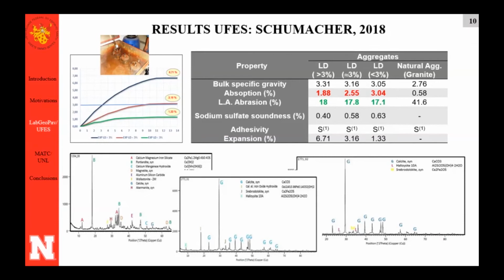And we also characterize those materials. The goal here was to see, because of expansion, what's going to change in terms of material characteristics, mainly the materials that are required for pavement use. And in asphalt mixture, if I change the level of expansion, does it change something in my mix design? Do I need more binder, less binder? How about the performance of the mixture, the Marshall stability, the indirect tensile strength? What's going to happen if I have different levels of expansion? Because if nothing happens, why do I need to cure? And curing takes time on the field, up to 6 months to reach the level that is required by the standards. So we took those 3 bags and we characterized common simple engineering tests that are required for pavement application.